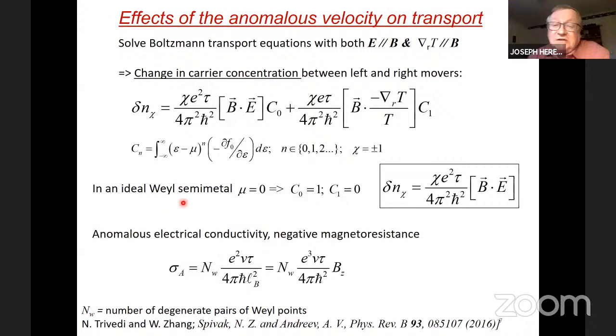If we have an ideal Weyl semimetal, which is to say we put the chemical potentials at the Weyl points, which I hope to prove to you that we can do, then this C0 becomes one, this C1 becomes zero, so the thermal gradient has no effect on the distribution of carriers between the chi equals plus one and chi equals minus one Weyl points. And we only have a change in carrier concentration, generation and annihilation of right movers and left movers respectively. So we only have an anomalous electrical conductivity that's given by the equation I showed you before.